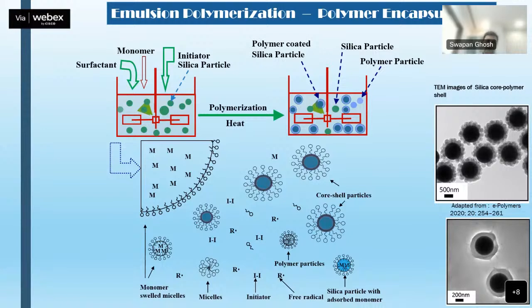So some sort of silicon oxide particle, if I modify it, as I said earlier, if one of them is not available, the reaction will not take place. So if I bind all the initiator, for example, on the silica particle, then obviously the reaction will take place on that surface, and in most cases will be forming the polymer coated silica particles.